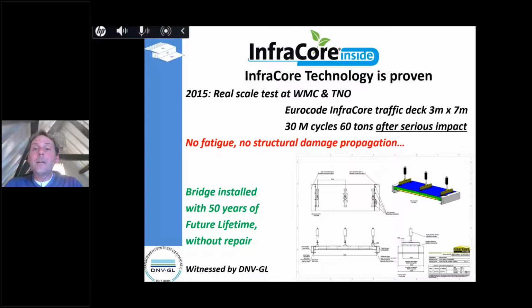So I stated that fatigue after impact will lead to local delamination, but it cannot propagate. That's not only a theoretical statement, it has been proven and validated, and it has been witnessed by DNV. What you see here is a 60-ton traffic bridge, which has been seriously impact damaged and has then been put into a fatigue cycle of 120 years, so 30 million cycles. And we have proven that the delamination, because of these local impacts, has not propagated, has not grown, which has led to the statement by classification societies that this bridge could be installed without repair for a remaining lifetime of 50 years. So I'm super proud of being capable of saying that a bridge can be seriously damaged, put into a fatigue cycle for 120 years, and can be installed without repair with a remaining lifetime of 50 years.